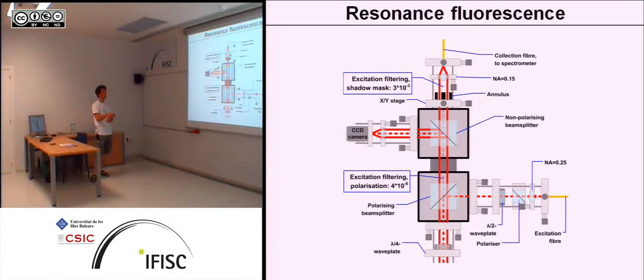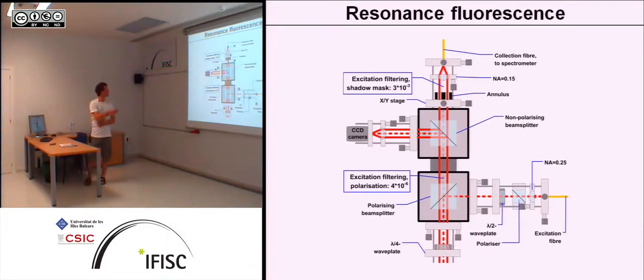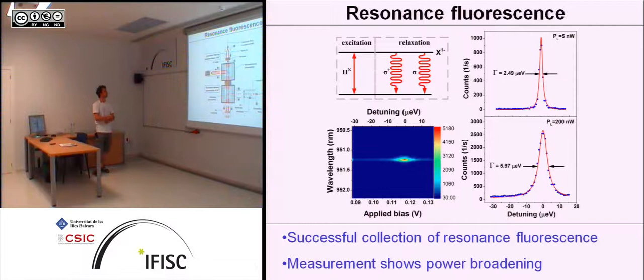but now the laser is collimated to a small diameter, whereas the quantum dot photons will basically fill out this whole lens here. And that means the first filtering is the polarizing beam splitter, so that will deflect this one again back this path, and thereby will result in an attenuation of 4 times 10 to the minus 6. But then we have a shadow mask over here which blocks the middle part of this beam, and thereby leads to another attenuation of the photons by 3 times 10 to the minus 3. So we should be able to collect photons, or the intensity of the collected quantum dot photons should exceed the number of collected laser photons.